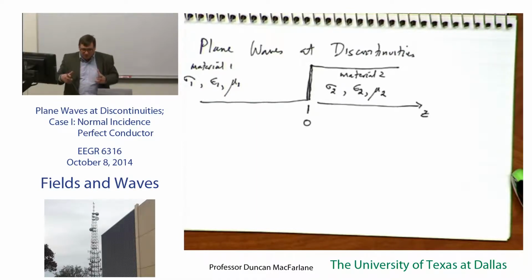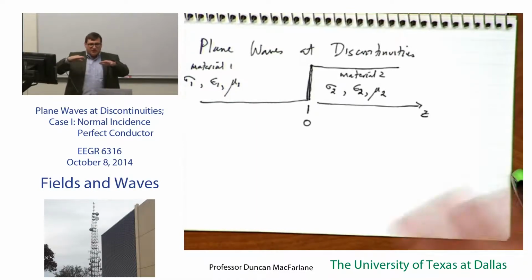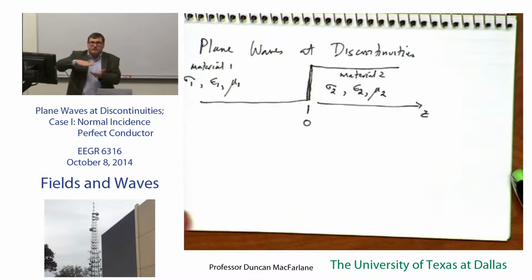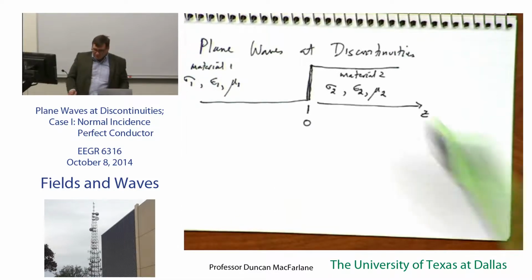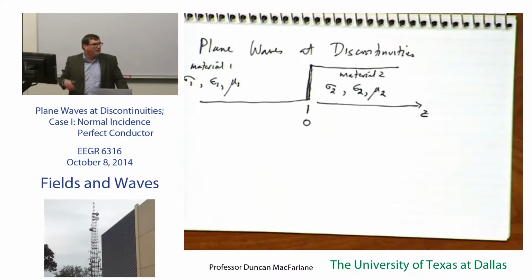And so if you think in terms of this, there are still imperfections after you do the fine one, but the imperfections, the scratches and the digs on that piece of wood, are related to the last or the finest sandpaper that you use. And so when you specify in the optics world that scratch and dig characterization, you want it small relative to the wavelength that you're working at, and that tells the lens polisher what grit to put in their slurries.